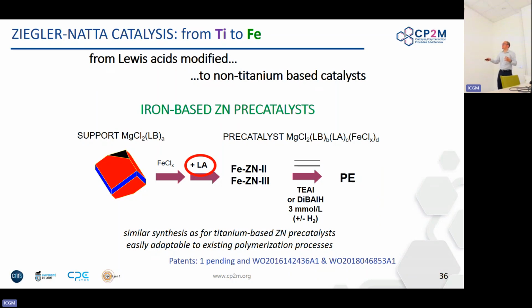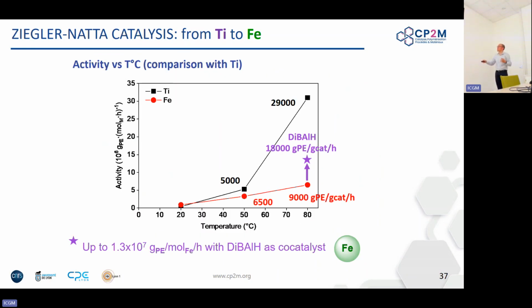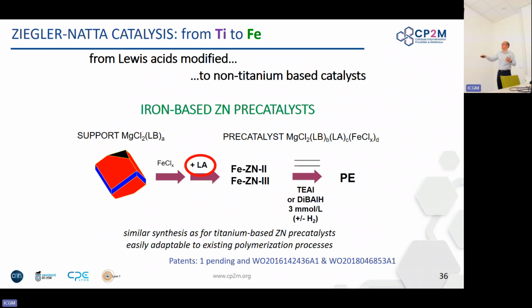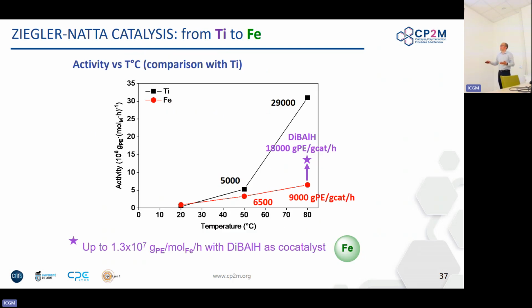You really need the Lewis acid treatment. Without it, you have no precatalyst activity. It will not turn into an active catalyst. And the alkylating agent can be conventional, or they're even better if they are aluminum hydrides. Okay, so diisobutyl aluminum hydride works really well. The activities are quite similar to what you can achieve with titanium.